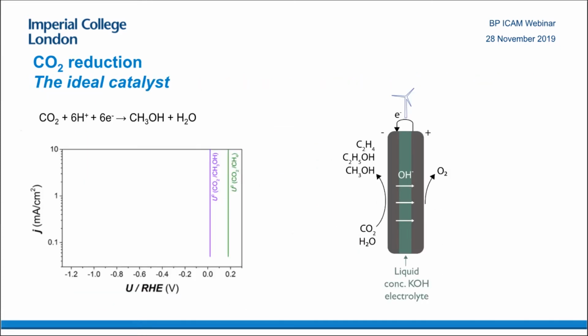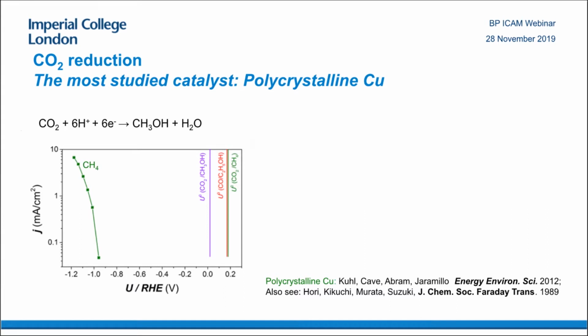So if you're doing CO2 reduction, what you really want from that ideal catalyst is very limited potential losses. This is what the current would look like. You have the thermodynamic potential, and this is the current that you'd want in an ideal catalyst. However, if you look at the most studied catalyst, polycrystalline copper, you can see there are huge potential losses, overpotentials around 1 volt.